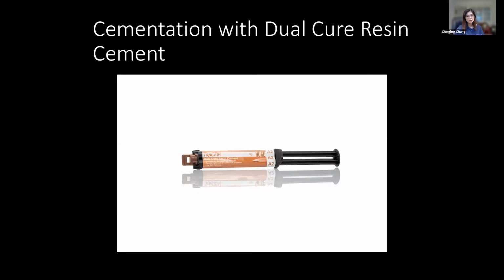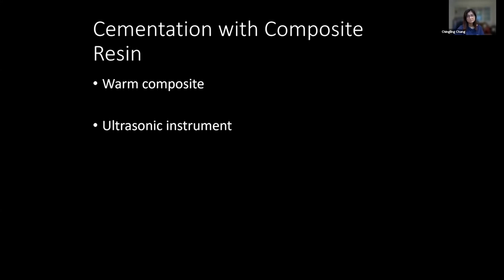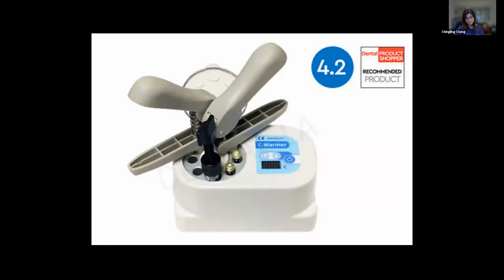And for the cementation, you can either use the dual cure resin cement, which is easier to handle, but usually they have a higher stain rate compared with a composite resin. But it has a benefit for some cases if it's very hard to polymerize some area of the tooth. Or you can cement the restoration with composite resin. You can either warm up the composite or use an ultrasonic instrument to increase the flowability of the composite, so you'll be able to insert the restoration into position.